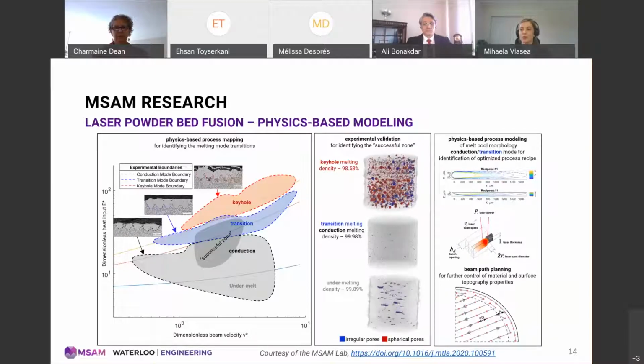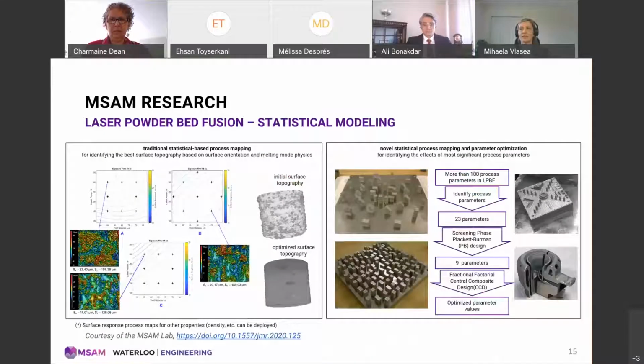Furthermore, we can model these melt pool morphologies to be able to stitch weld lines together to create low defect parts. For some instances, statistical models can be deployed for creating process maps and for optimization of process parameters. These approaches are quite powerful, but do rely on a larger set of experimental points to inform a model.